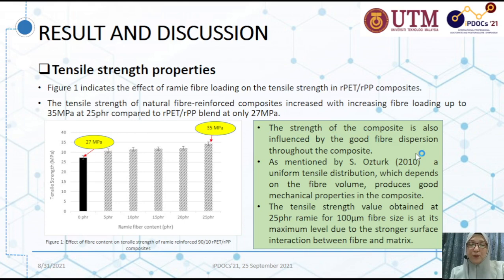The strength of the composite is also influenced by the good fiber dispersion throughout the composite. As mentioned by S. Ozturk 2010, a uniform tensile distribution, which depends on the fiber volume, produces good mechanical properties in the composite. The tensile strength value obtained at 25 phr ramie for 100 micrometer fiber size is at its maximum level due to the stronger surface interaction between fiber and the matrix.